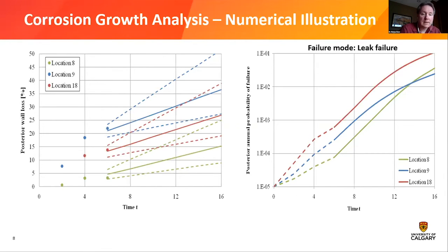Here's just an example where we consider a stochastic process for the actual corrosion growth, and we include all the measurement errors. We have here in the left figure on the horizontal axis the time. We see here the ILI measured points. And then we see here the predictions. The full lines are the mean values, and the dashed lines are sort of 80 or 90% confidence intervals.